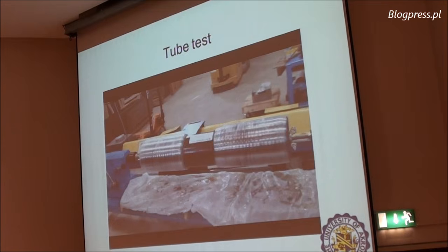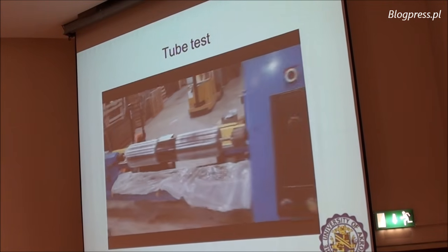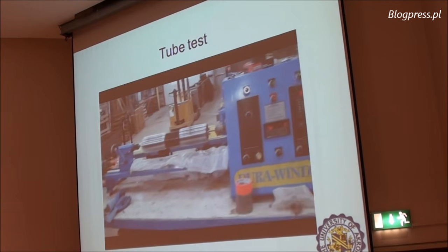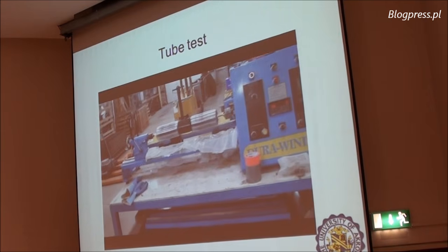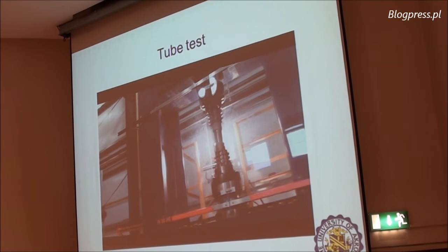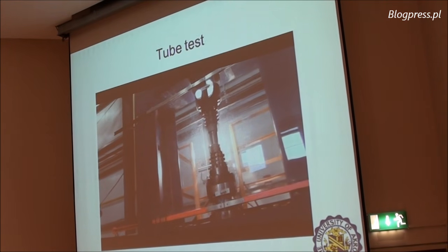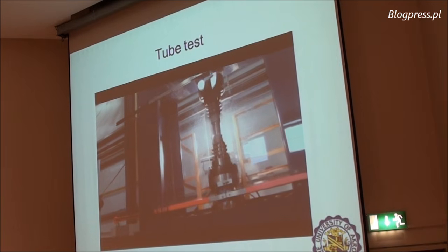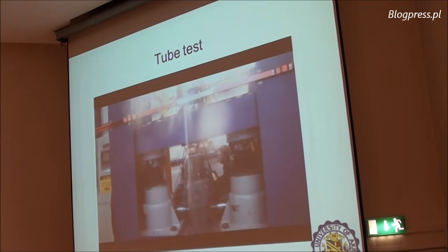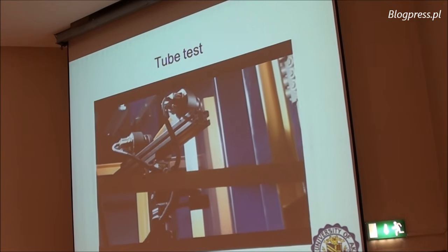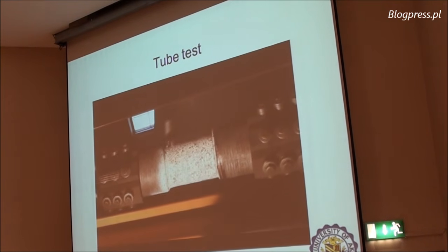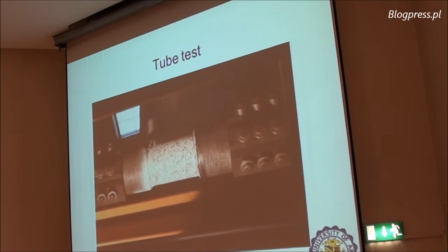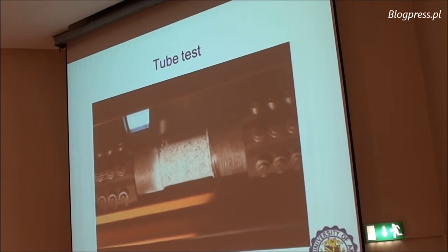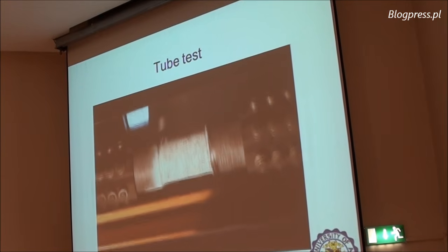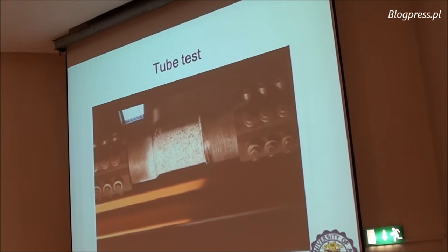specimen. This is showing some video of making the gripping area, which we had to overlap with extra material and then machine it. So that takes a lot of preparation time for each tube, and you can now see the test itself in the machine. You can see my graduate student sitting behind and controlling this process of testing. And pretty soon you can see two cameras measuring through DIC the spots that are painted on the surface of the specimen, which will eventually be post-analyzed in the computer and show those fringes of the strains.